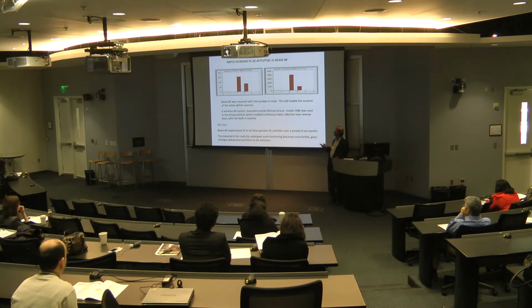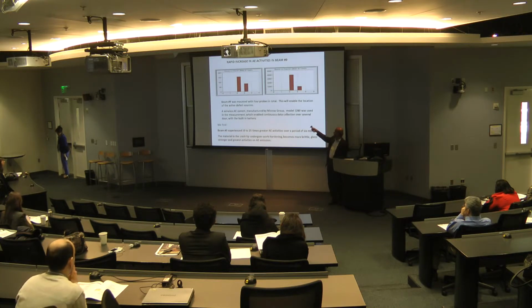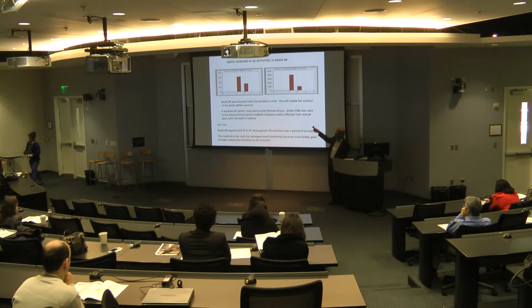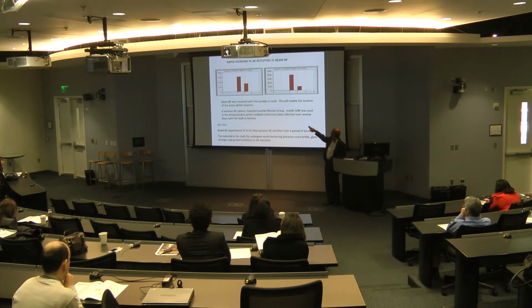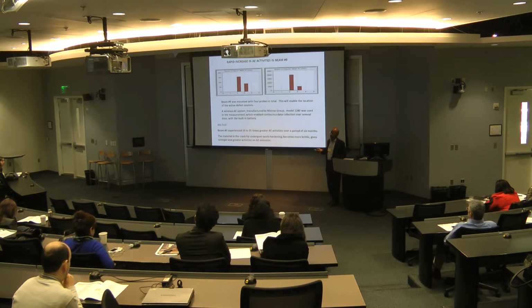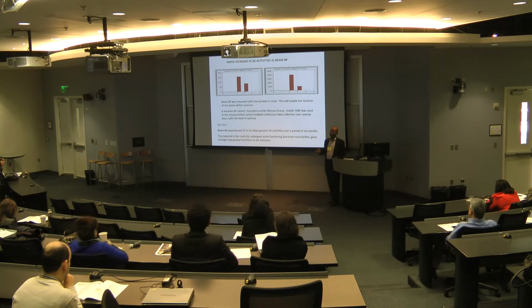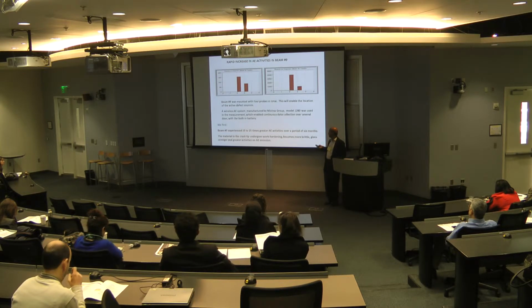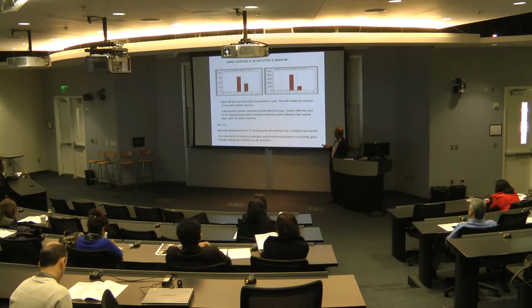And this we carried out on beam number 9. The left diagram was the result taken in September. The right diagram was carried out in the January, February time period. The scale is not the same; the scale is different. If you see, the activity has increased 10 to 25 times in a period of about 5 months, suggesting that it is very likely that the defect is expanding, propagating.